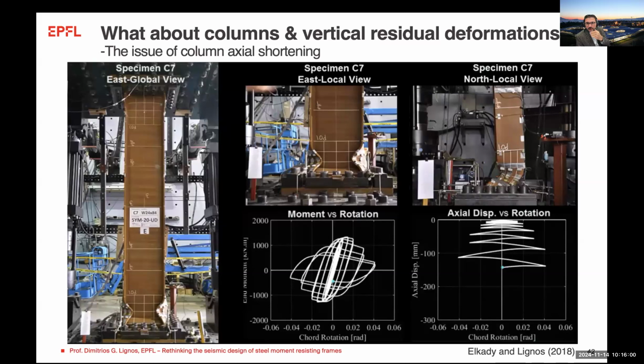Now, if you're looking at OpenSees, as you said, discretization would be important, but usually discretization is important if you're dealing with softening, because you get strain localization. So in this case, if you are using, let's say, a fiber-based model, not a continuum model, I would have to be careful to use a regularization scheme with a given discretization, so that I can alleviate the mesh dependency I'm going to have.